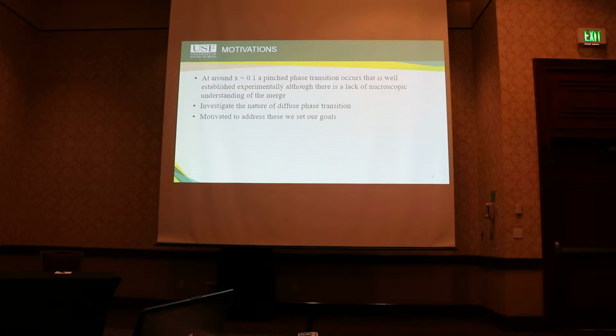So at around 10%, the pinched phase transition occurs, and while this is well understood experimentally, there's a lack of a microscopic understanding for why this phenomenon occurs. Also, the associated peak of the dielectric susceptibility for BZT is much broader than BTO, which is sometimes referred to as the diffuse phase transition, which is also something that we would like to investigate.